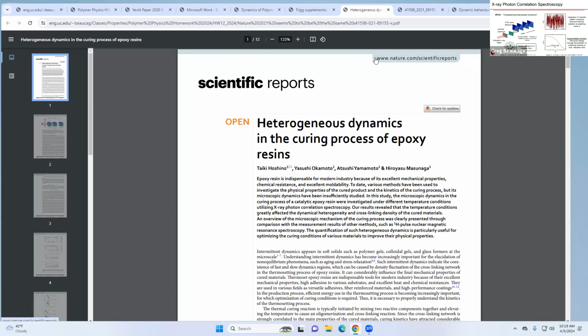And if you see in the schematic here, we've got a bunch of these speckle patterns all backed up next to each other. So what we do is we just turn on the detector and we basically film a movie, a high frame rate collection of these speckle patterns in time, where each one is encoding and showing basically where these particles are in time, all right? So it's a way to kind of literally make a mini movie of the movement of all those little particles at that nanoscale.